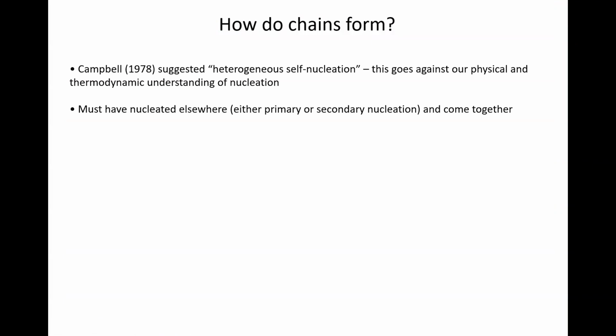Well, the Campbell idea is heterogeneous self-nucleation, where you have a grain of chromite and then you nucleate another grain of chromite on it. The first grain stops growing, and this one then starts growing, and then another one will nucleate. And I put it that this goes against our physical and thermodynamic understanding of nucleation. That's a polite way of saying that if he brought that idea to a first-year undergraduate tutorial, it would have been demolished in a few minutes. It doesn't work, okay? So these grains must have nucleated elsewhere, either by primary nucleation, heterogeneous or homogeneous, or by secondary nucleation. And secondary nucleation is a process of nucleation which relies on already having a grain of that mineral somewhere in the system.